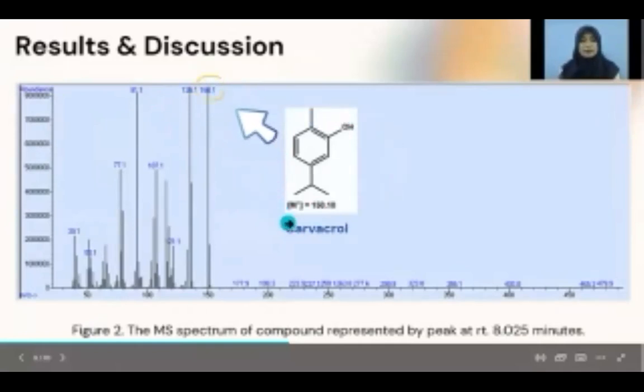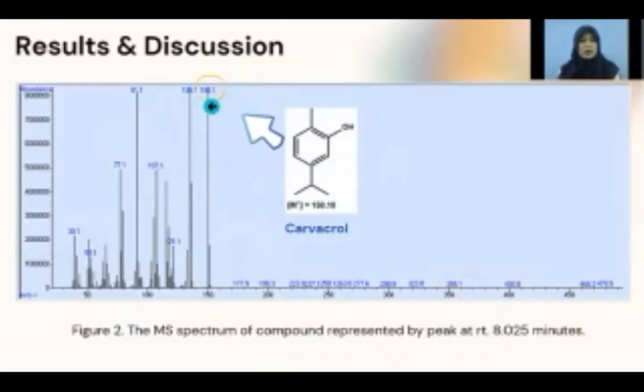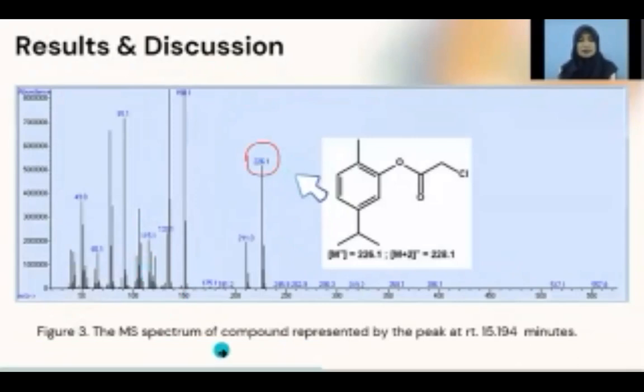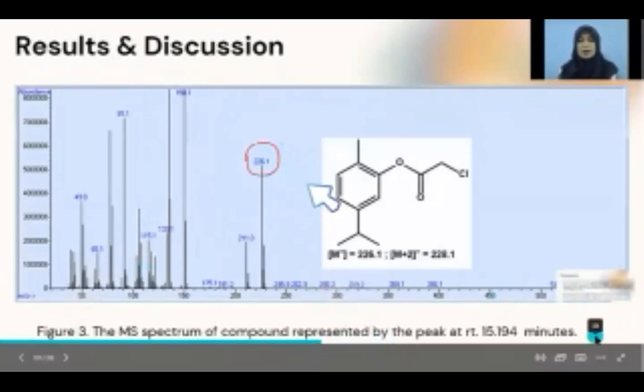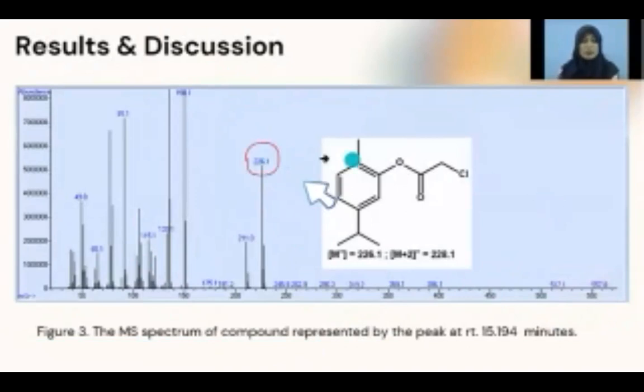To validate our prediction, we can see the MS spectrum of the compound represented by the peak at retention time of 8.025 minutes. Figure 2 shows a peak with M/Z value of 150.1, which corresponds to the molecular ion of carvacrol. Next, we also can see the MS spectrum of the compound represented by the peak at a retention time of 15.194 minutes. Figure 3 also shows a peak with M/Z value of 226.1, which corresponds to the molecular ion of carvacryl ester.